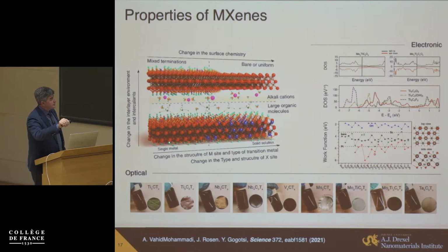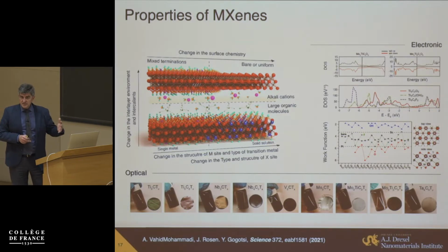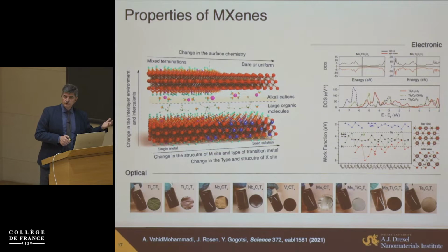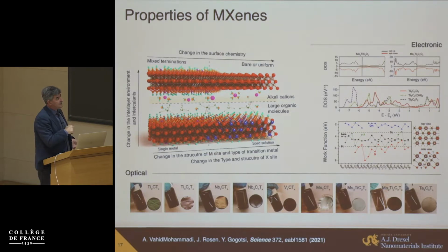And because the majority of MXenes have, well, even the one with 2 layers, you still affect properties much less than graphene. So in graphene, you get oxygen, OH on the surface, make it water-soluble, graphene oxide, and you kill the conductivity completely. In this case, you can graft molecules on the surface, and you can keep the conductivity in Ti3C2 because it will be the electrons, for example, of titanium that provide conductivity in this layer.